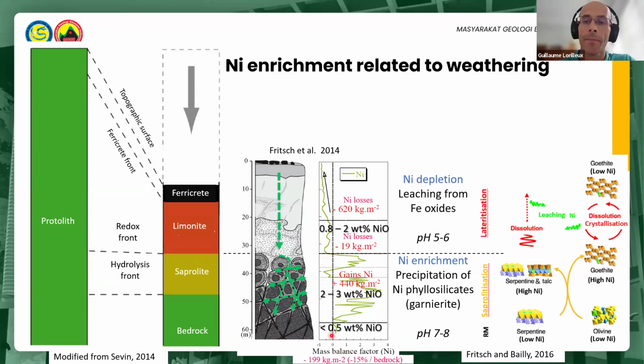In the saprolite, considering a mass loss of 70%, the theoretically computed residual enrichment alone would result in 1% nickel, considering the same density and grade hypothesis as before. This shows that residual enrichment is not sufficient to explain the higher mean nickel grades which can be found in saprolite. Other factors are therefore necessary to explain the observed nickel grades.